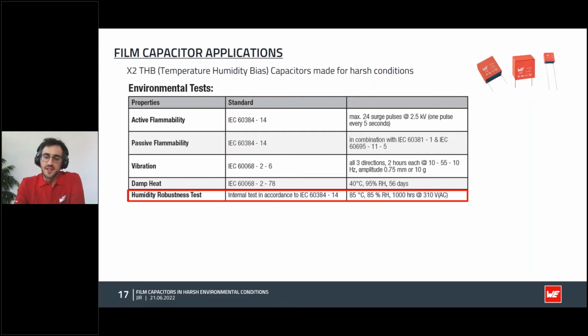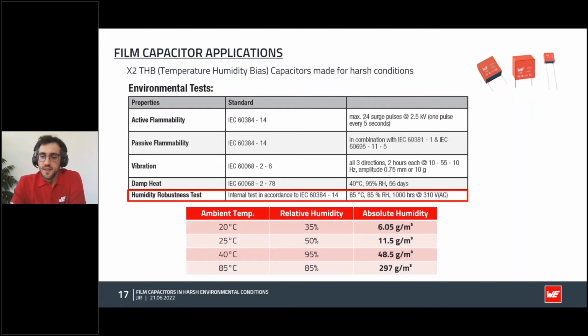Taking into account that to reach 85% humidity at this temperature, there is a huge amount of water in the air. For reference, you have this table with some common conditions used in datasheets. The first one is considered ideal laboratory conditions at 20 degrees Celsius and 35% humidity. We only have 6 grams of water in a cubic meter of air. But in the 85 test, there is almost 50 times more water in the air.